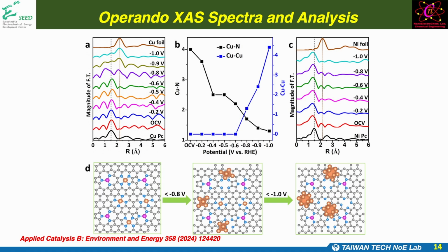So we try to understand what happened. We perform this operando X-ray absorption to monitor the status of this single atom. If the potential is higher than minus 0.8, it would stay at the single atom state. Once lower than minus 0.8, some copper single atoms will reduce to a copper cluster. Even further, the copper cluster becomes bigger, but the nickel still remains in the single atom state. I won't go into the details. So that's the reason: if you can control the dual atoms to still operate at a single atom state, you can get a higher Coulombic efficiency of C2 product, the ethanol product, through this dual single atom catalyst.